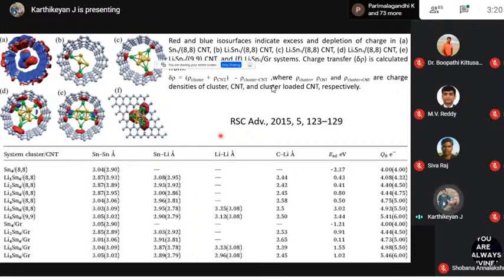So we are always interested, as theoreticians, in interaction: what type of interaction is present between these tin-lithium alloys and the CNTs. So we studied the charge transfer between the lithiated tin clusters and CNTs, and in all these cases you can find that the lithium is actually interacting with the pi ring of the carbon atoms in the CNTs. So there is a cation-pi type of interaction in all these composites. That gives a better stability for this tin-lithium cluster